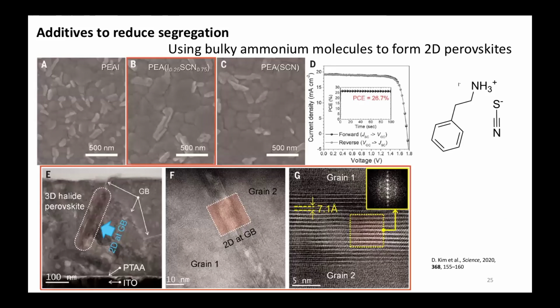And people have been able to visualize that. Here you see a layer of all kinds of crystals next to each other. If you zoom in at a certain region, here you see these little layers. This is a 10 nanometer scale. In between two bigger crystals, there's a 2-dimensional structure that is created by the addition of these alkyl ammonium additives. So it's like a special interface on the nanoscale between two crystals.